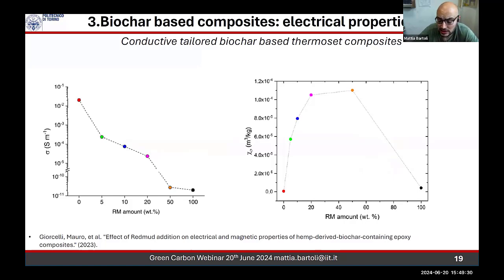And it is quite interesting because you can have a smart material with high conductivity with the increment of crystallinity, so the increment of conduction of the final composite, using red mud that is quite hard to manage and is a pain to dispose of. But here we can use it mixed with, in this case, hemp, producing a functional biochar that has a cost that covers the process. So it's quite interesting if you are thinking of reshaping certain kinds of applications.